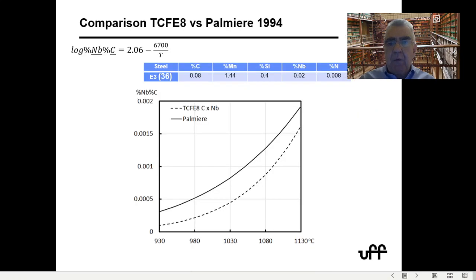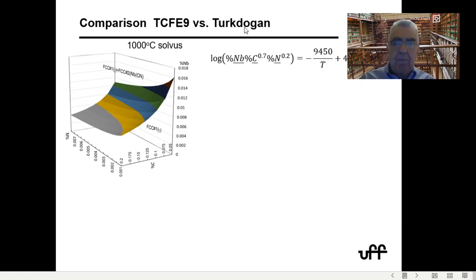Now, when you compare the values calculated by this CALPHAD methodology with some classical solubility products, you see, for instance, if you do it for one of the steels that Palmieri used experimentally, that the value he proposes with this formula is quite different from the value that you calculate with the thermodynamic databases, considering that the compound is not exactly niobium carbide, but a carbonitride. The same happens if you take Turkdogan's compound, in which he assumed a fixed stoichiometry, because this is not really happening, that you have a fixed ratio of carbon to nitrogen.